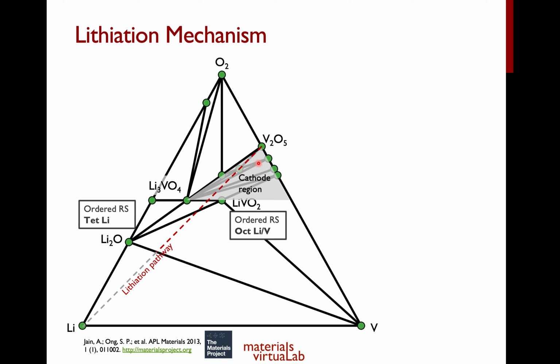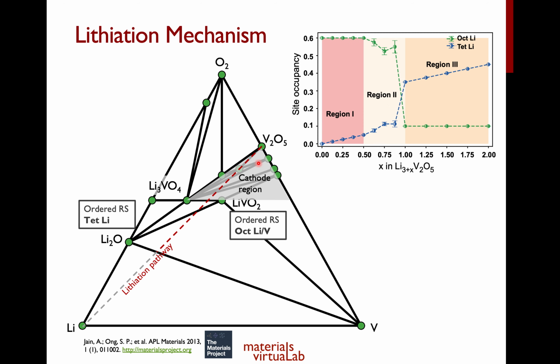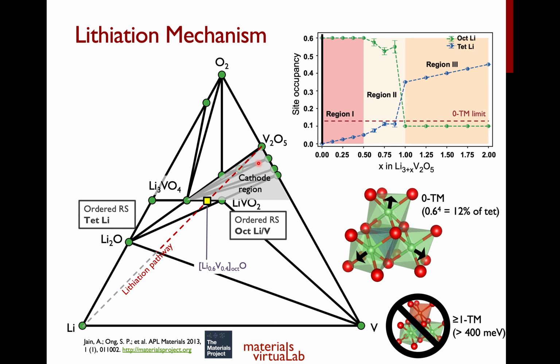All right. So this is using DFT calculations. We computed different orderings for the disordered rock salt as we attempt to insert more and more lithium into Li3V2O5. Let me now go through our observations step by step. At the start of lithiation, when x is equal to 0, we have Li3V2O5.